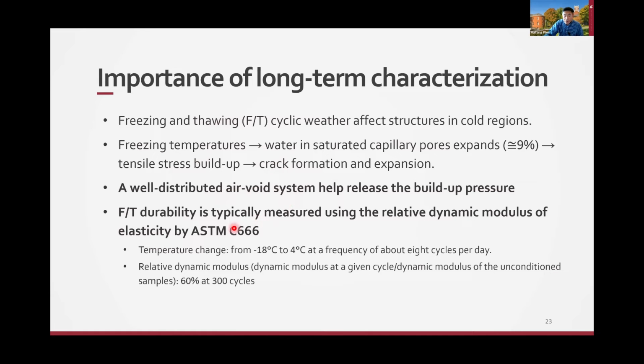Typically you do the freeze-thaw in a chamber, based on ASTM C666, cycling the temperature from -18 to 4 degrees, with 8 cycles a day, and each time you measure the dynamic modulus. The ASTM gives a recommendation that after 300 cycles of freeze-thaw, you're supposed to retain the dynamic modulus at 60% or higher. So that's one indication.